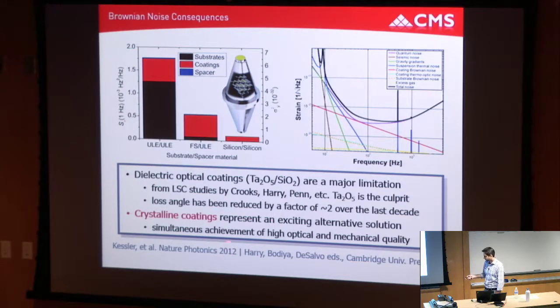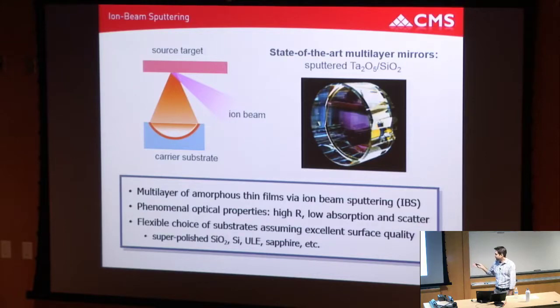And our crystalline coating technology is really interesting because we're looking at a room temperature increase in mechanical quality factor by a factor of 10 and a cryogenic increase of more than a factor of 100. So it's a significant increase over this sort of factor of two when making small adjustments to the ion beam sputtered films. So I keep mentioning ion beam sputtering.